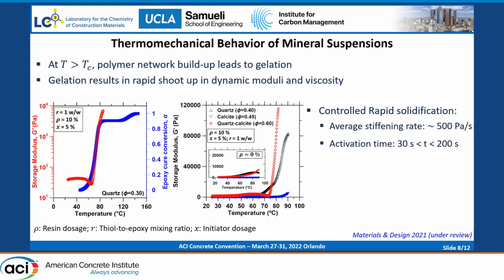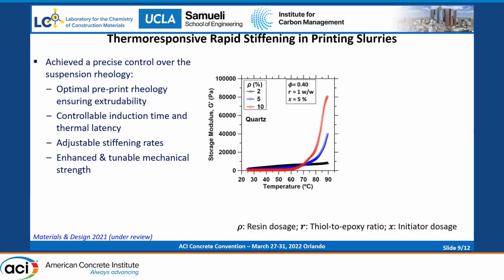As you can see, in these suspensions there is essentially no increase in modulus until we reach the activation temperature, and beyond that we see a very rapid increase in the modulus. And there is a stark contrast between the suspension with and without resin. Without resin, there is no noticeable change in the stiffness. Even though, depending on the minerals and the volume fraction, we can have differences in the thermoresponsiveness, we still get an average stiffening rate of 500 Pascal per second, and the activation time can be as low as 30 seconds. A few more examples of the control that we have on the thermoresponsiveness.